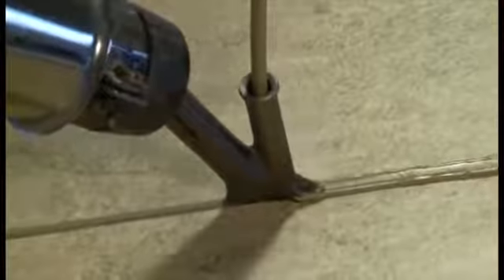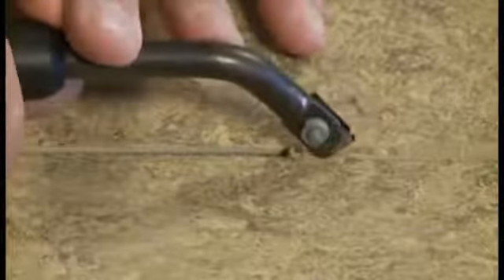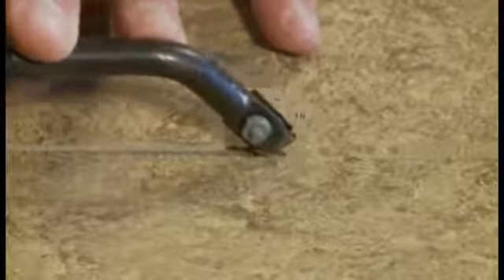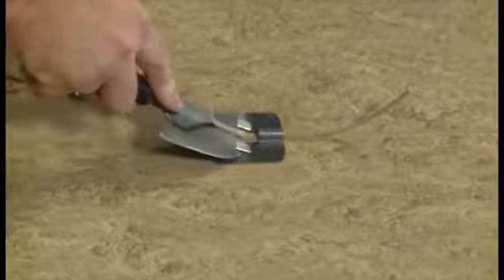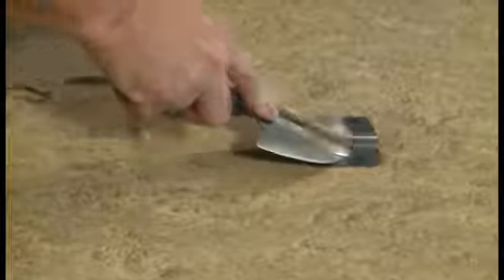Once the first part of the seam is welded, you will need to change directions. Make a ramp by skiving the weld rod 1 to 2 inches from the end of the welded seam. Hand groove the skived section of the weld rod. From the opposite direction, continue welding up the ramp and overlap the initial weld for several inches, creating a splice. Skiving the weld rod should be done in two passes to minimize concave seams.